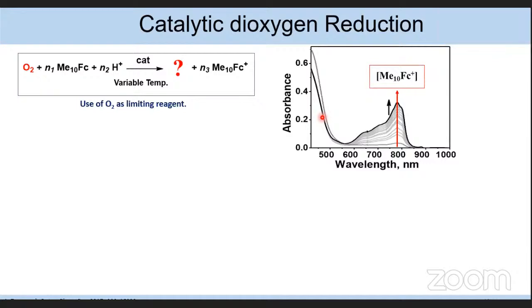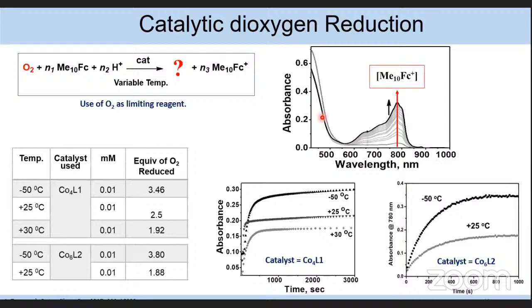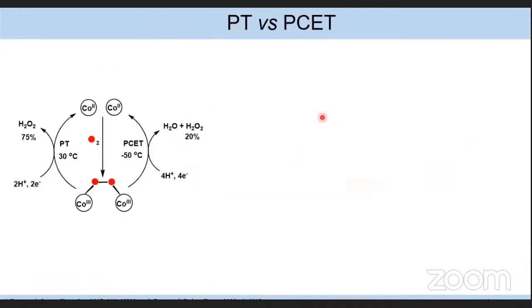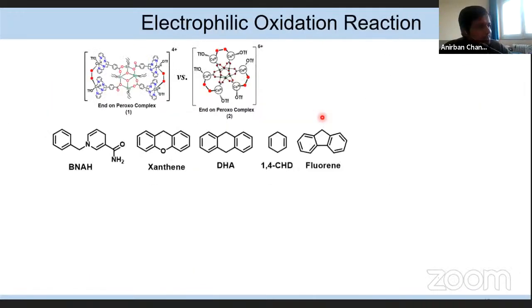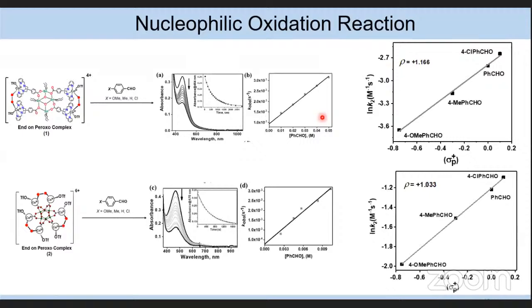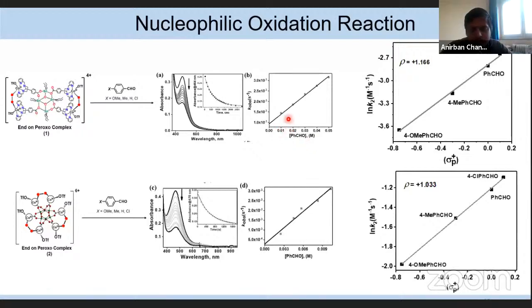Okay, and when you plotted that k2, why do you see an intercept? When you plotted the rate of reactions against the substrate concentrations, why is it not passing through the origin? Exactly, at 25 degrees centigrade my complex, I mean these peroxo intermediates, suffer from self decay. So I have to consider the self decay rate, and this is the self decay rate. So if you subtract the self decay rate, it will pass through the origin. Yes, exactly.